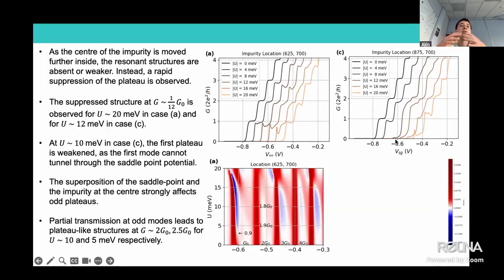And this is because in the saddle point, so in the middle, the bottom of the energy profile of the structure is higher. So then when we add some hill and well-like impurities there, the hill-like impurities will make it even further up. So the first ground state will not form and transmit there. So instead, it will pass through continuously, but the second mode will be able to exist in the system. So if I were to not have a randomized disorder, but have a kind of smooth profile or a third middle gate or something like that, then I would see that jump to the second plateau quite clearly. You can also move it around and have different orders of those jumps as well.